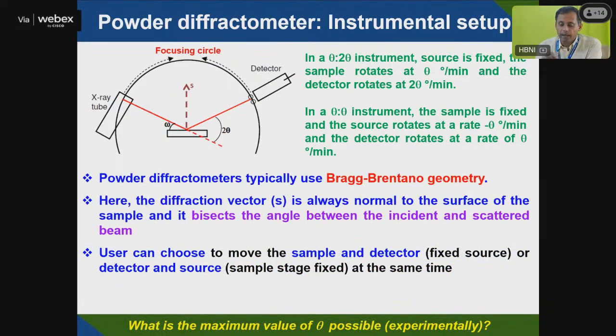If you see the powder diffraction instrumental setup, you have an X-ray source, a sample here and a detector here. You can see they are on a particular circle. That means the sample is at the center, and the X-ray tube and detector are on the perimeter of this circle. In powder diffraction, that circle is called Bragg-Brentano geometry. So the X-ray tube, source and detector should be arranged in this way.